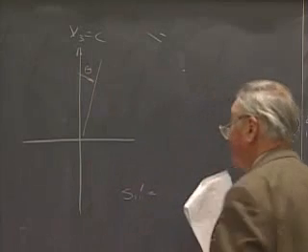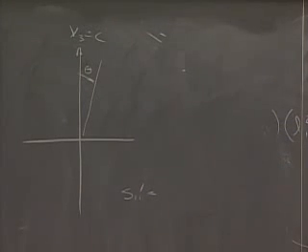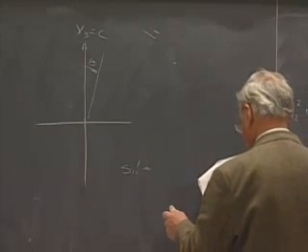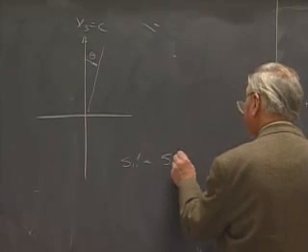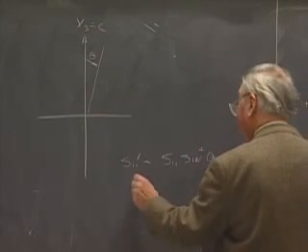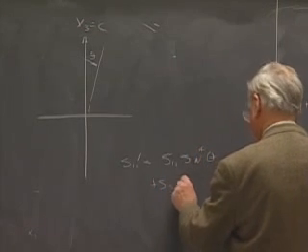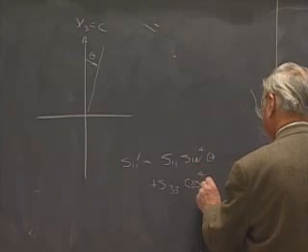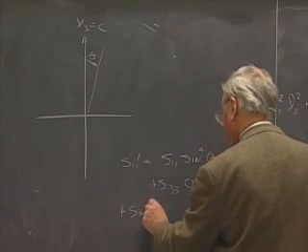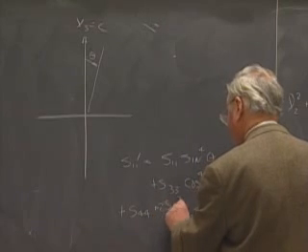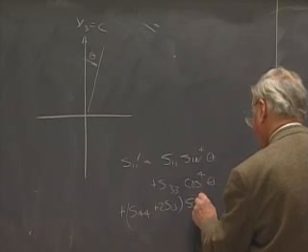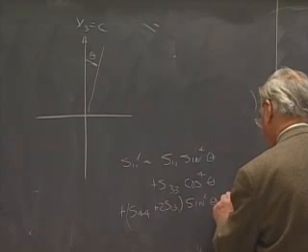That's the only parameter we need to examine the variation with, since it's a surface of revolution. S11 prime is equal to S11 times the sine of theta to the 4th power plus S33 times the cosine of theta to the 4th power plus S44 plus 2S13 times sine squared theta cosine squared theta.